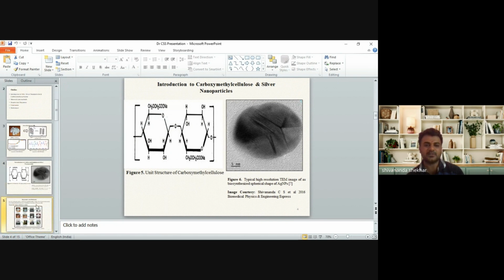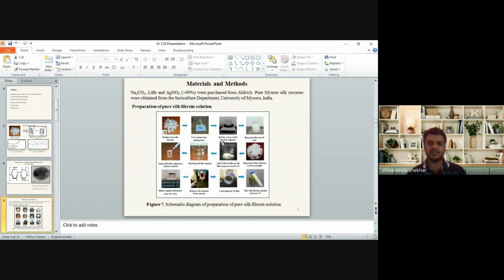Then we have adopted a standard methodology to prepare the silk fibroin solution. This is the schematic representation of the preparation of silk fibroin solutions. Here we have adopted a standard silk processing method. In this work, we have taken the raw silk cocoons, cut them into very small pieces, and then boiled them in hot water for around 1 hour, using sodium carbonate. After 1 hour, we took out the silk fiber, squeezed it, and kept it in a petri dish for 1 day to dry.